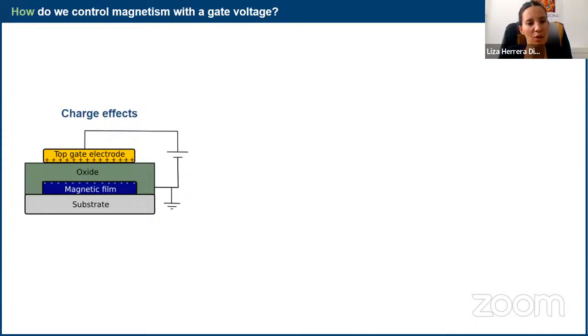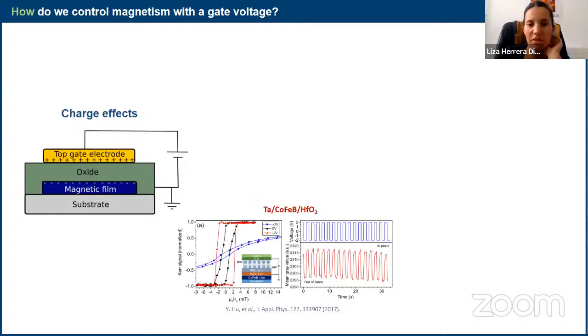So before I show you more about ionics, let me give you a quick overview of things that have been done with charge effects. So here there is an example: tantalum, cobalt, iron, boron, hafnium oxide. You will see hafnium oxide a lot today because this is a study that we did in our lab. So we like to use hafnium oxide a lot because it's a material that is very well known from the memristor community, but then I will get to that in a minute.